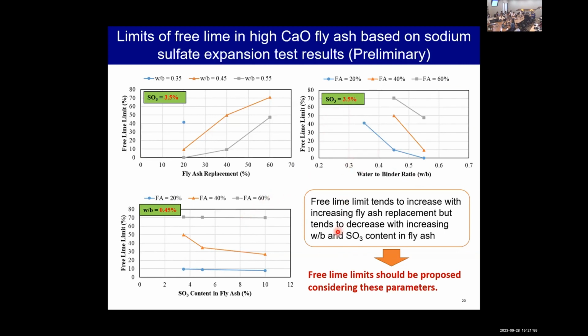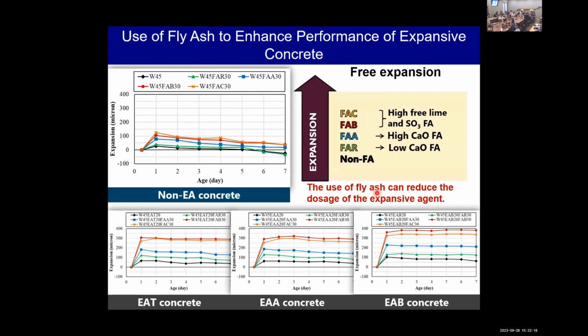It can be seen that the free lime limit tends to increase with increasing fly ash replacement, and it tends to decrease with increasing water to binder ratio and increasing sulfur trioxide content in fly ash. So from this data, the free lime limit should be proposed considering these parameters, not just one single value.